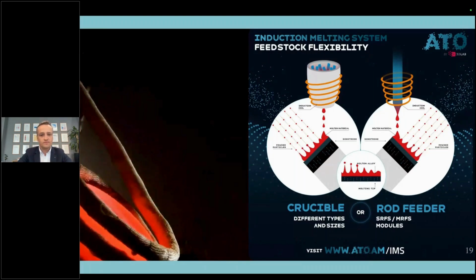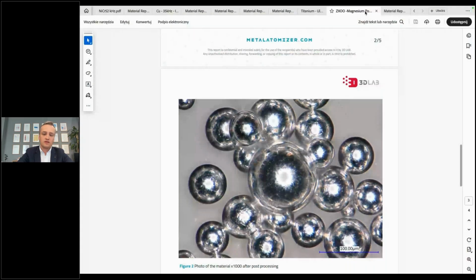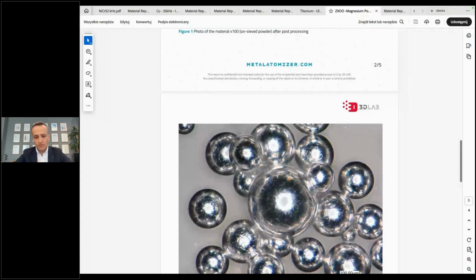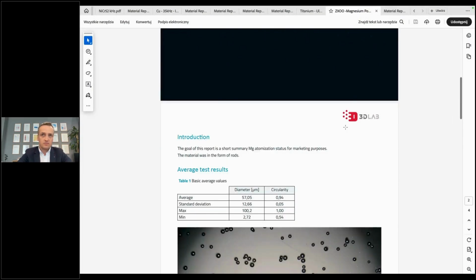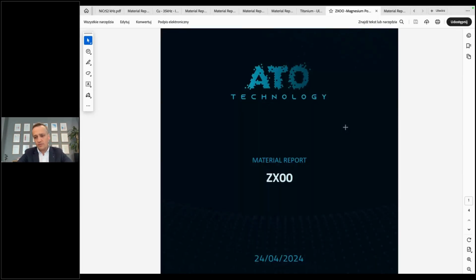I can tell you a great example. One of our customers had a problem with atomization of magnesium. They have been a user of our ATOLab basic module since 2023. But once they asked us to switch to magnesium, they found out that the evaporation of the magnesium was a little bit too high. That's why we proposed that they work with the induction melting system.